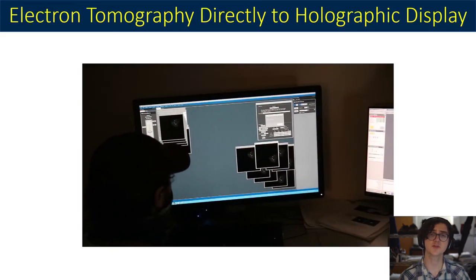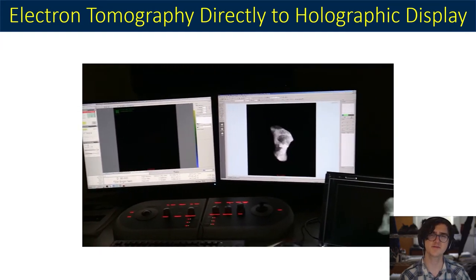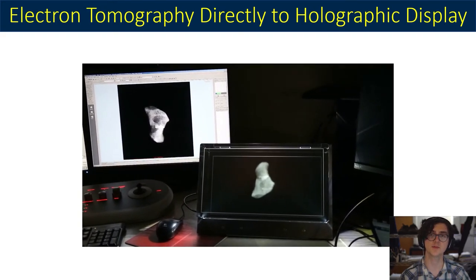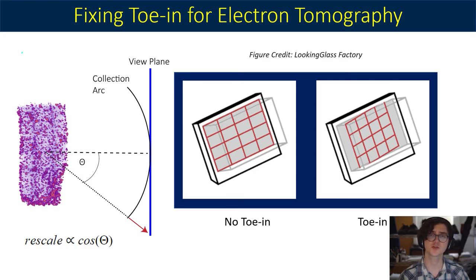It is also possible to generate a 3D visualization using just tilt series data. This technique is quick — with fast data acquisition, it's possible to go from microscope to holographic display in around 5 minutes, because we can leverage how the hardware projects data to simply re-project our tilt series such that it appears in 3D. Projection data collected on a microscope by rotating the object is analogous to moving the camera around an object in an arc, which isn't dissimilar to the view plane method associated with holographic displays. However, it is necessary to account for differences between these two camera motions. Failure to do so will result in an effect dubbed toe-in — a distortion caused by the eyes receiving incorrect monocular cues. If images are taken along an arc, all images show the object as the same size; however, higher-angled images on the view plane should be smaller due to being further from the 3D object. To account for this, a small scaling must be applied to each image, mapping from the collection arc onto the view plane. We perform this simple affine scaling to help mitigate the toe-in effect.